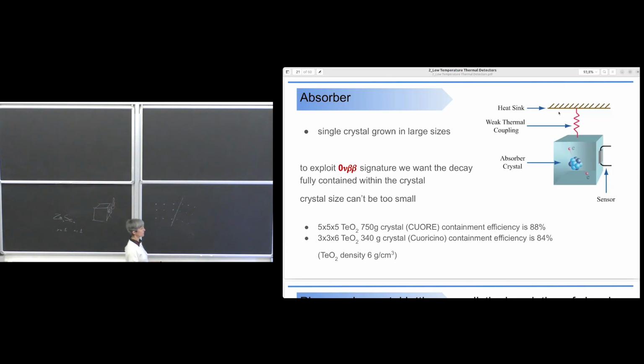And just to give you an idea, in the case of tellurium dioxide crystals, in the case of CUORE crystals, the containment efficiency is 88%. That means that 88% of the decays are fully contained, therefore the 2 electrons deposit their energy and are stopped inside the crystals. While if you move to a smaller crystal, this is decreased, but not so much. And you need to know that the density is 6.